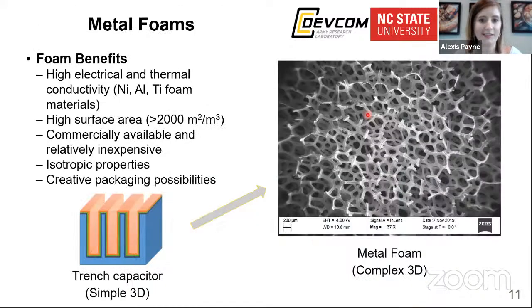So this is why we approached this problem from a different angle, using metal foams. We want to use metal foams as our bottom electrode because, first of all, they're 20 microns thick versus 20 nanometers thick everywhere. They're true metal, so they have both high electrical conductivity and high thermal conductivity. They have high surface area. They're commercially available and relatively inexpensive.